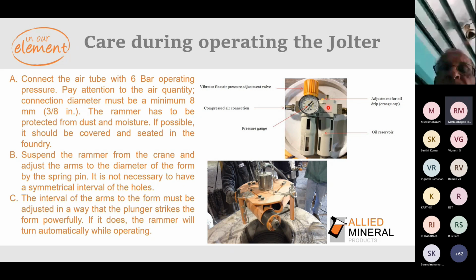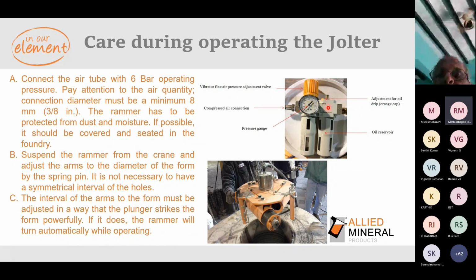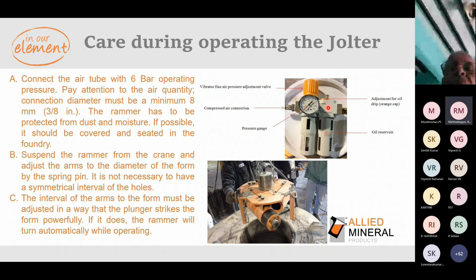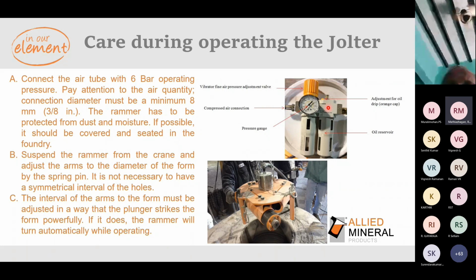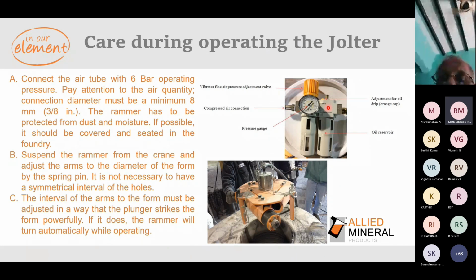I'd like to bring everyone's attention to operating this tool. First, this tool should be used only for compaction, because I have seen in the market people use it for de-airing also. They don't do any kind of forking. They just fill the material, introduce the vibrator inside, and start the vibration. But this motor is designed only for compaction. So we recommend forking the material at least 5 minutes for each layer, then introducing the vibrating motor and starting the vibration.